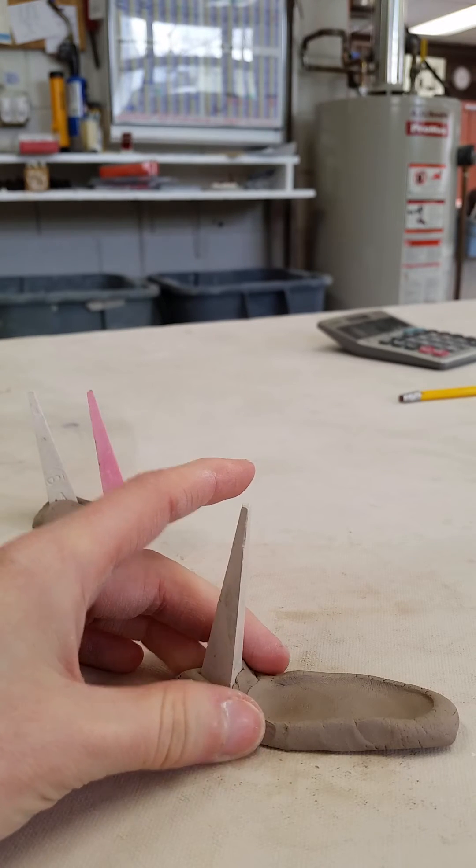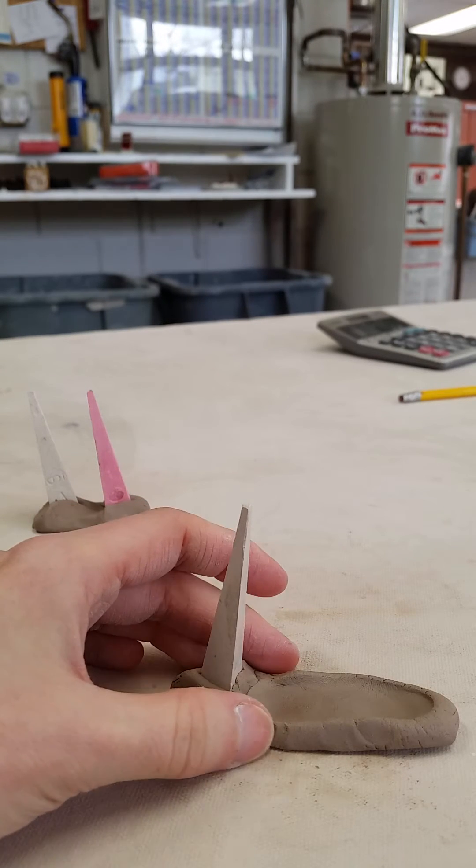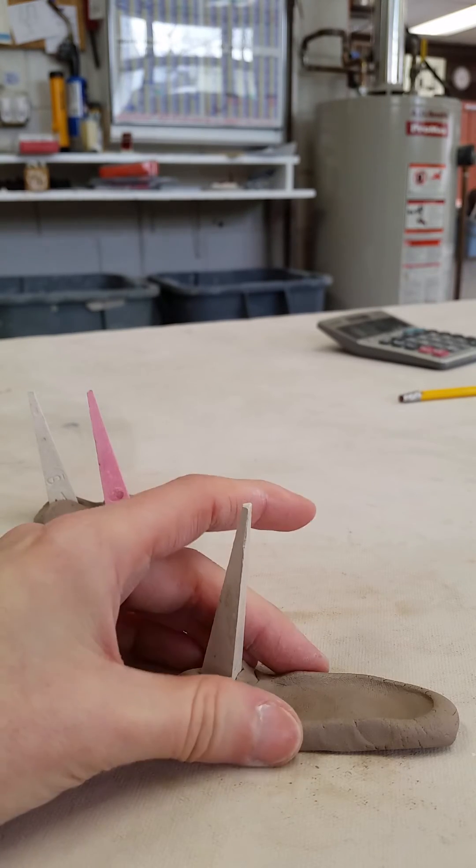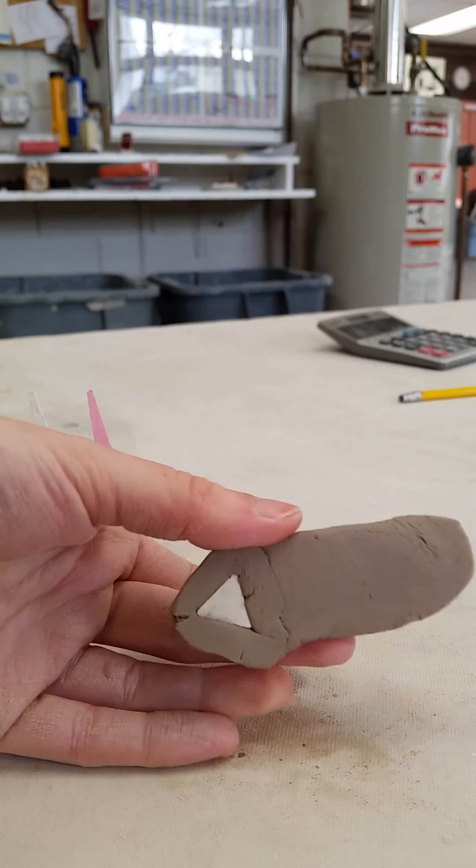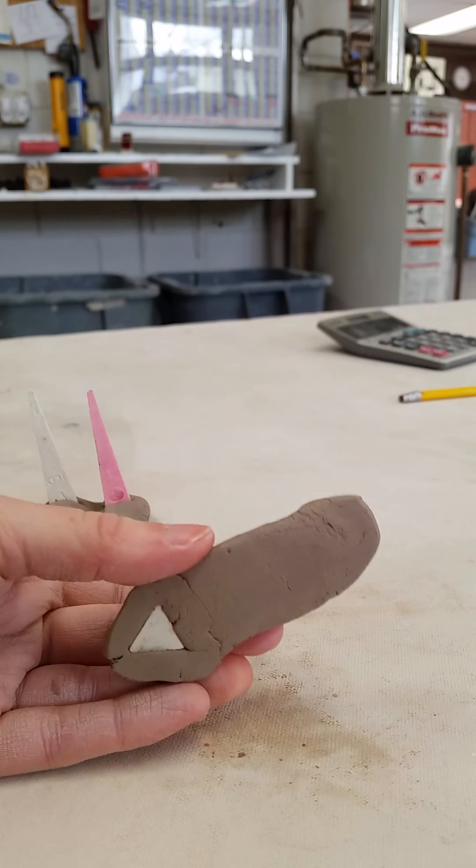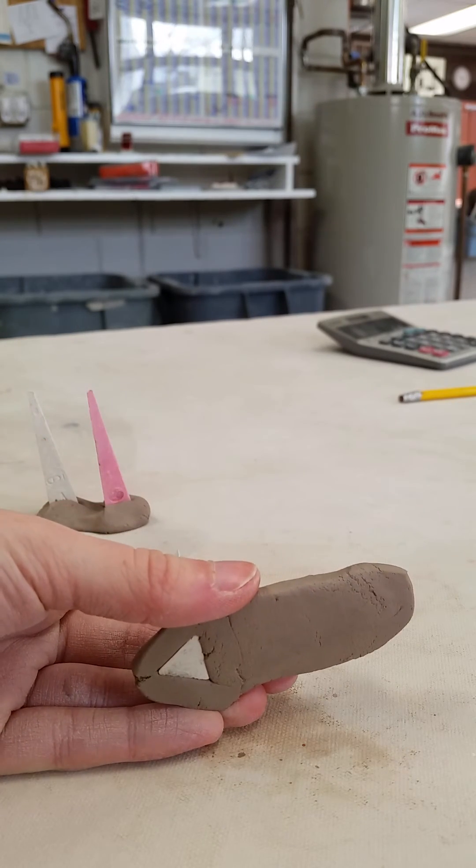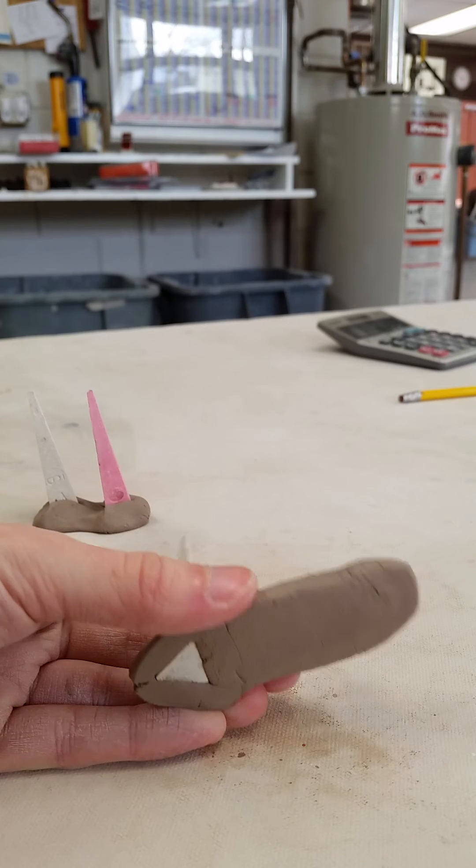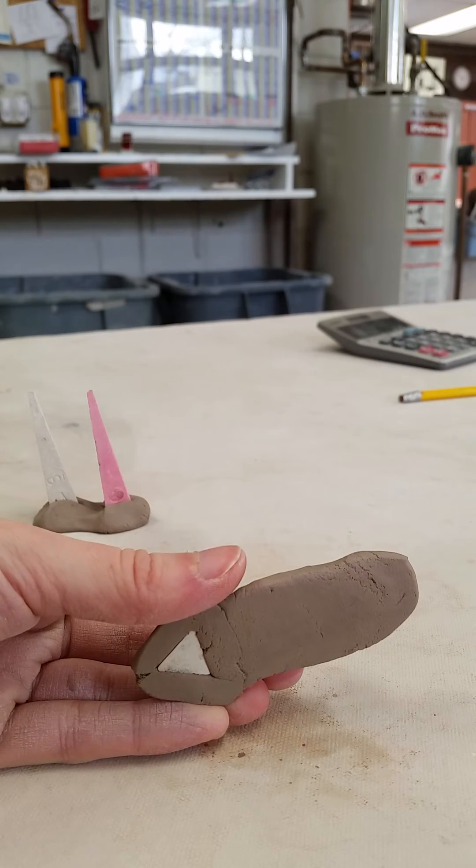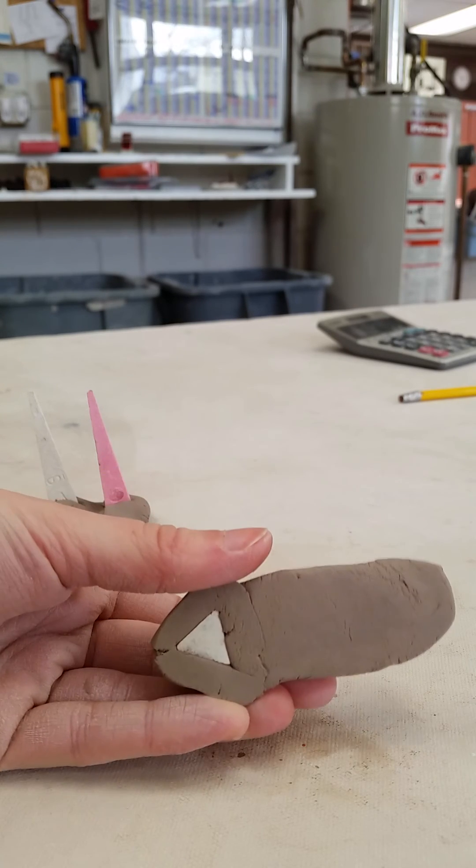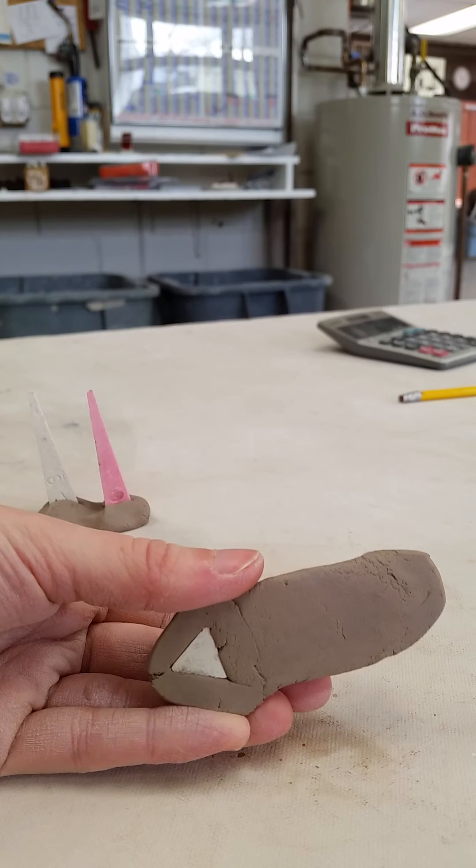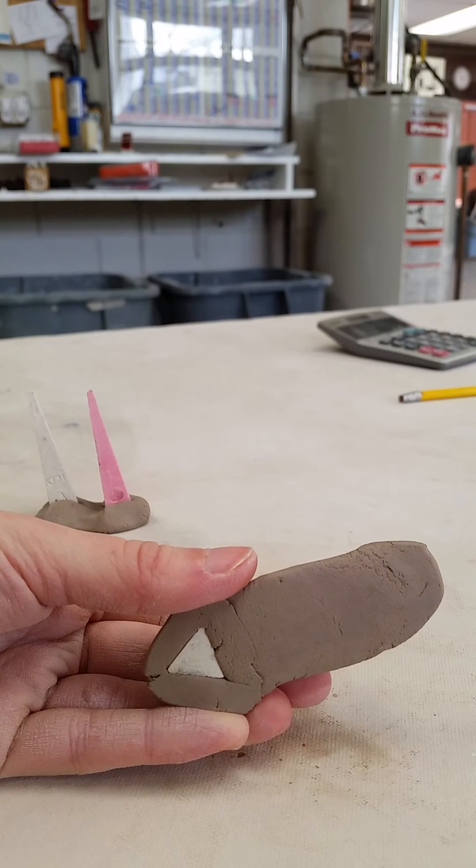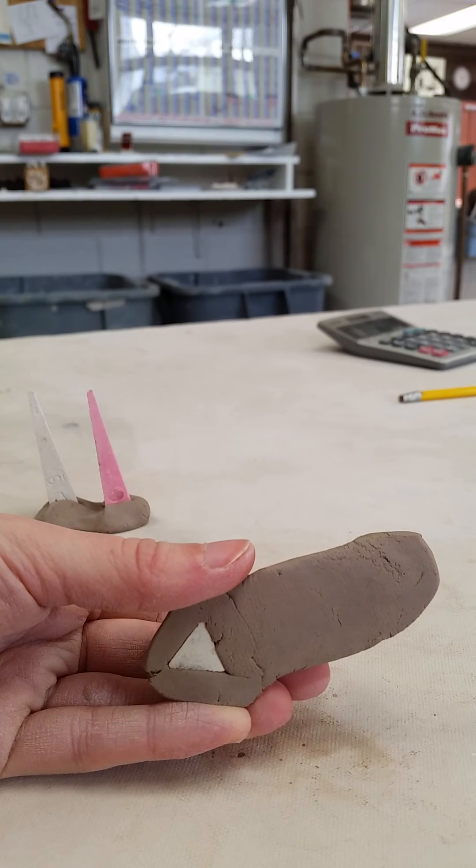One thing about making cone packs this way: if you do expect your cones to melt a lot, if you're using a low cone to signify when you have reduction or salt, you're definitely going to want to put a waster underneath. Because of course this cone is going to be in contact with a kiln shelf. So just put a little waster underneath there, or maybe a little extra kiln wash, and you will be good.